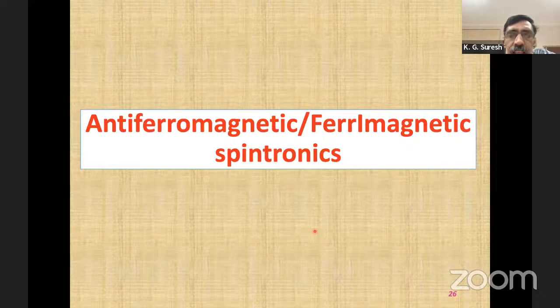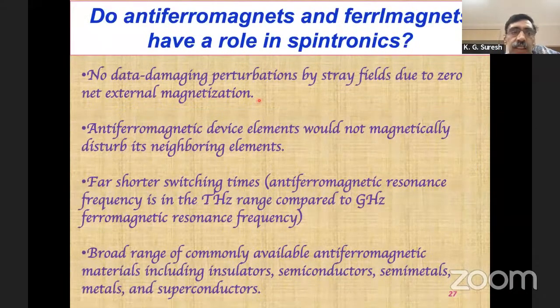Now, as I mentioned, in the last 5-6 years, antiferromagnetic or ferrimagnetic spintronics has become very important. So far, everything has been ferromagnetic. In many of these conferences, there is a separate session for antiferromagnetic spintronics. So why are we interested in this? Because it is antiferromagnetic, the signal to noise ratio improves, especially when you are reading, because ferromagnets have these stray fields. It will affect internally also the regions where the data is stored. So you want to try to reduce these kinds of stray field effects.